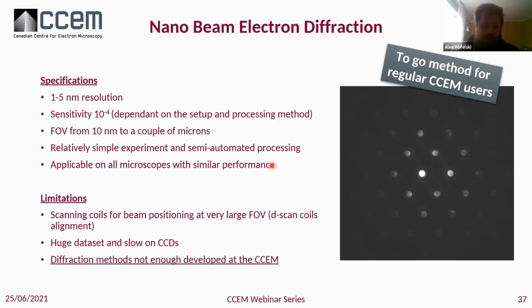Regarding the limitations, huge data sets, as we talked about, gigabytes in a few seconds on the K2. So then you need to have a very efficient processing method. Just to open the data is already a challenge. And then, I would say the diffraction methods are just not developed enough at the CCEM. That's actually our strongest limitation.